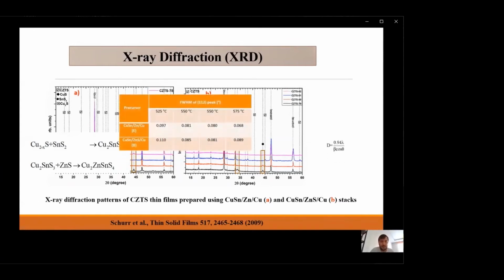To investigate the crystalline quality of the films, the Debye-Scherrer formula is used here. As you can see, according to the Debye-Scherrer formula, the crystalline quality is inversely proportional to the full width at half maximum values here. As the temperature increases, you can see the full width at half maximum decrease. It means that the crystalline quality is also enhanced.